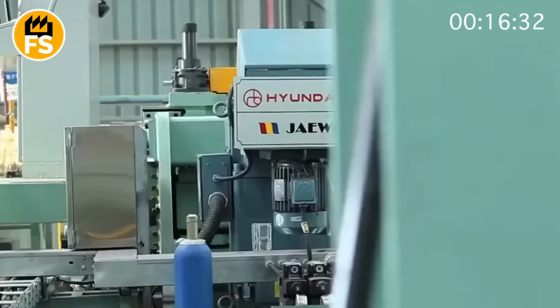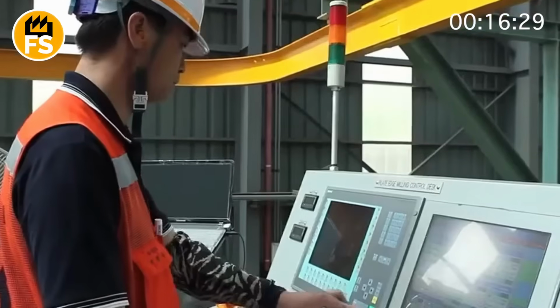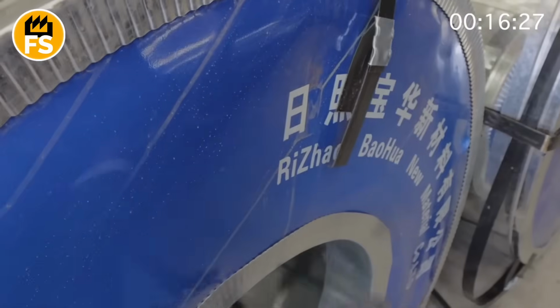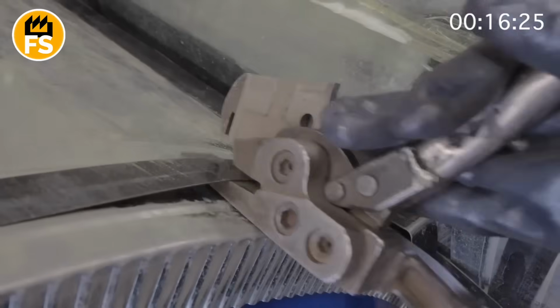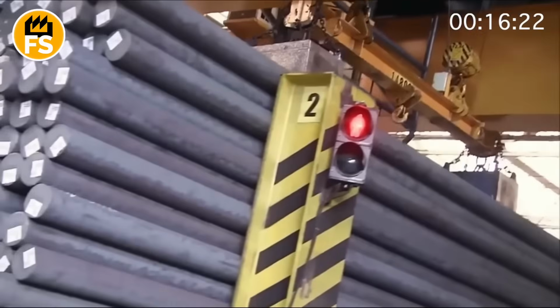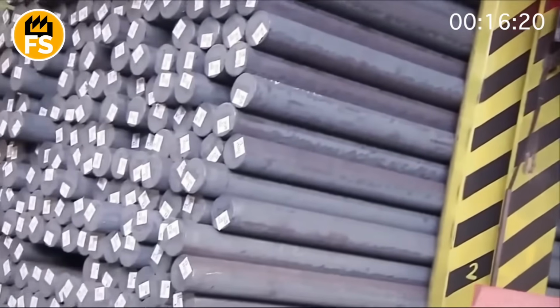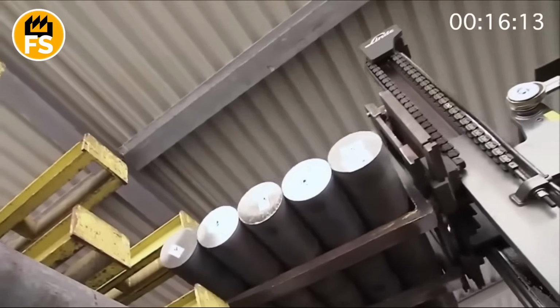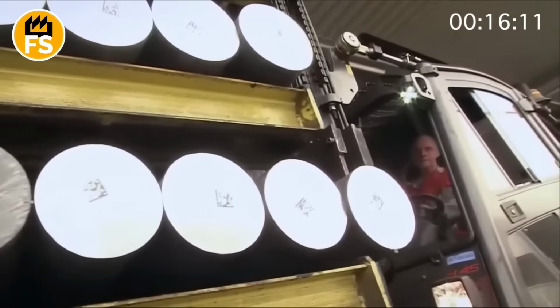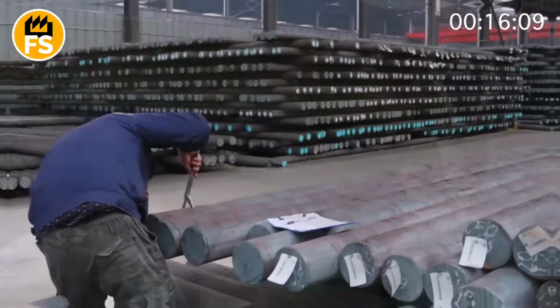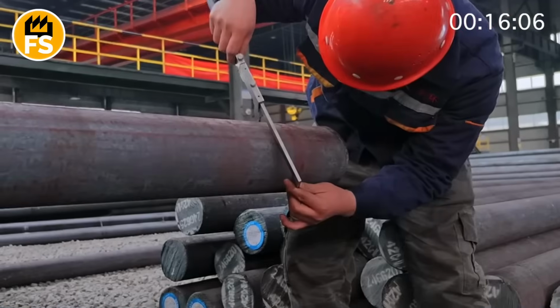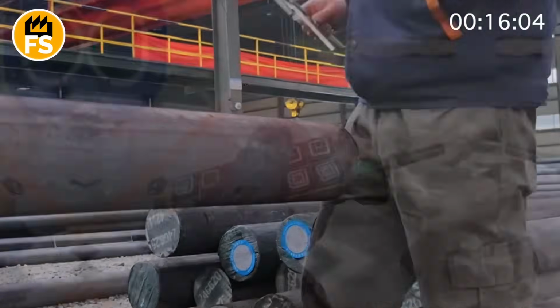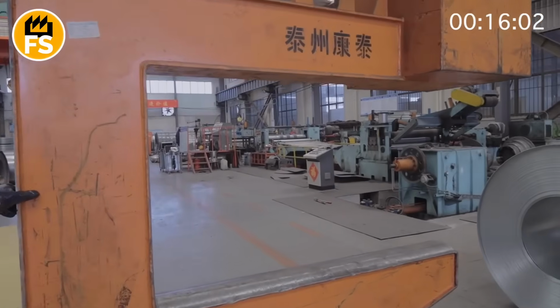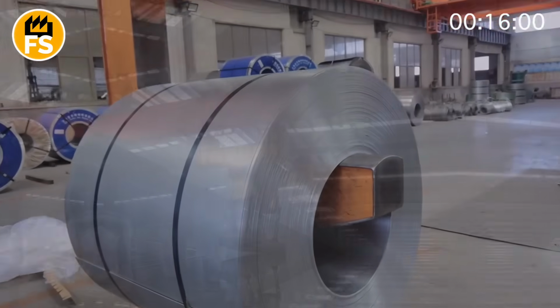The billet is coated with a conductive gel, like for a human ultrasound, and a transducer is moved across it. Special transducers shoot sound waves at a frequency of 5 MHz. That's 100 times higher than submarine sonar. This is how they search for cracks and inclusions of foreign materials within the billets. The system builds a 3D map of defects with an accuracy of 1/100th of an inch. If it finds a saboteur, the billet is marked with red paint and sent to metal hell for remelting.